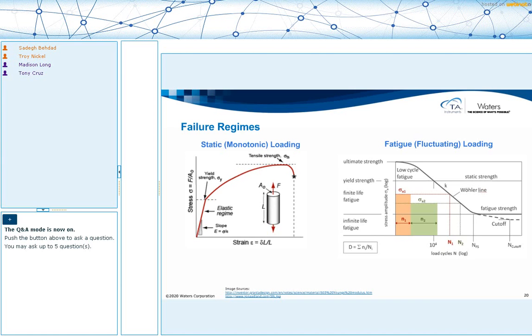So say at stress level 1, which is the higher one, your material could survive capital N1 number of cycles, and you exposed it to small n1 number of cycles. So you are consuming, say, 30% of your material's life. Then you reduce the stress to stress level number 2, the green one here. At level 2, your material could survive capital N2 number of cycles. But now you had initially exposed it to a higher stress and consumed 30% of its life. So now we are only going to consider the remaining 70%. So you can look at the summation of number of cycles exposed to number of cycles that it can take at each stress level. And the closer this overall summation gets to 1, the closer to failure you will be.